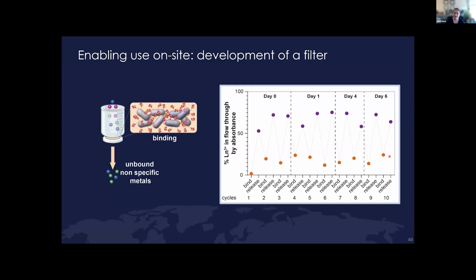I should also note that currently rare earth separation is performed with about 300 liquid-liquid separation steps that require chemicals such as kerosene and phosphate ligands that are known to be very cancer-causing, carcinogenic. And so what we see here is basically that we end up with these rare earths in water because we're not adding any organic solvent in order to bind or release them, and stable protein-based materials across 6 days without requiring cold chain. So now we have protein materials that we can use for separations that don't require the same consistent temperature and controlled environment transport that you would normally associate with biologics.